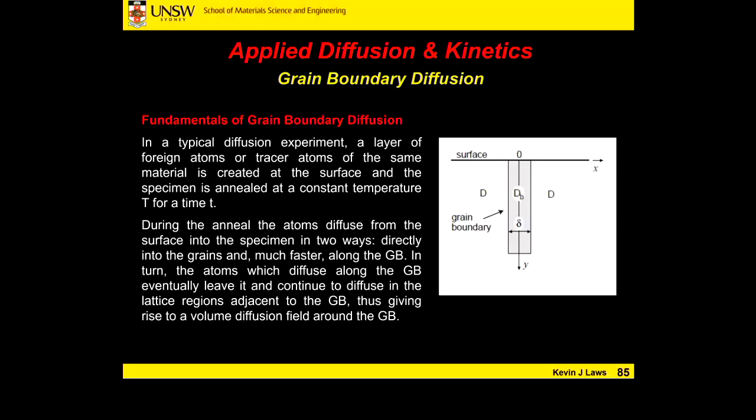With semiconductors, grain boundaries are bad, because we get accelerated diffusion of whatever our surface layer is, the dopant, into our grain boundaries faster, and this creates a localized concentration. When we have a localized concentration of elements that we use for doping, the properties will be different from place to place in our semiconductor.